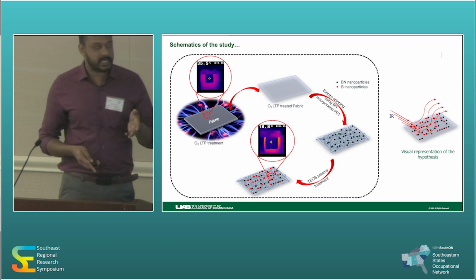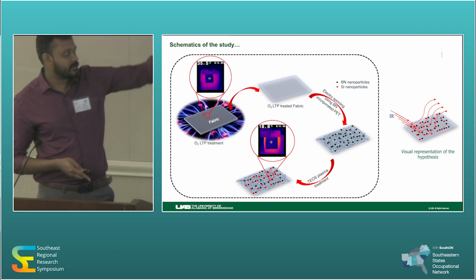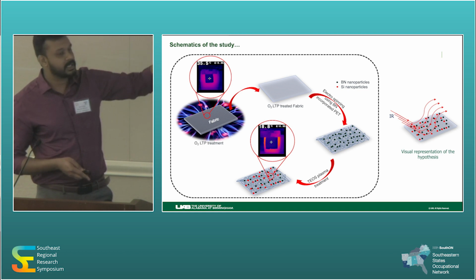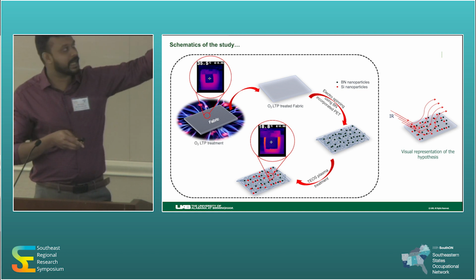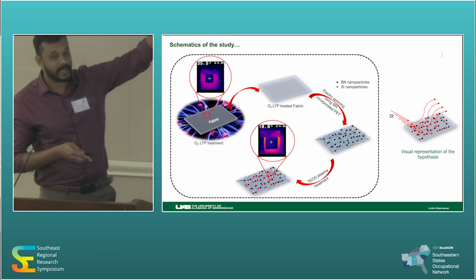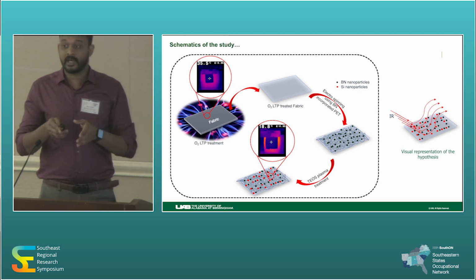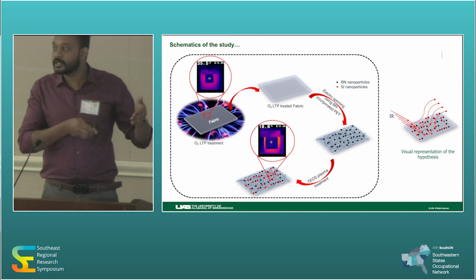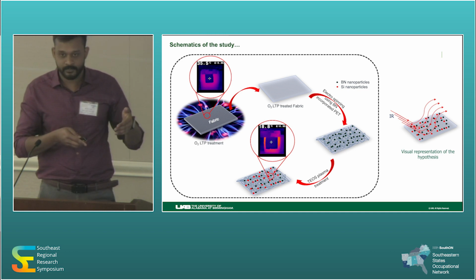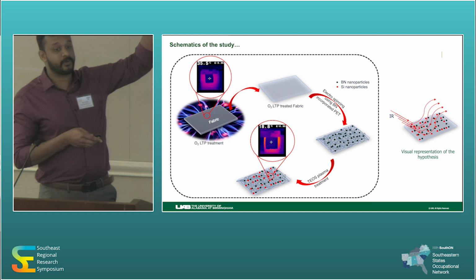And this is the entire schematic of the study. Our substrate is fabric, and without any treatment, with the IR camera, it shows a temperature of 35.5 degrees, while we are providing a hot plate at 40 degrees C. So it has an effective temperature of 35.5.